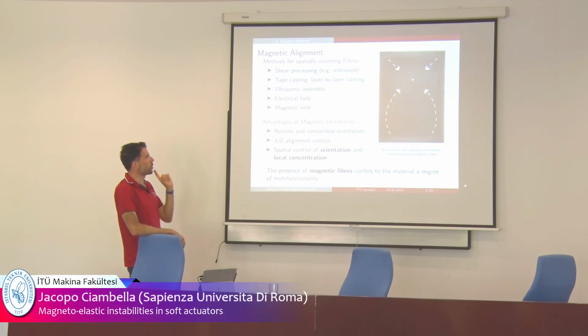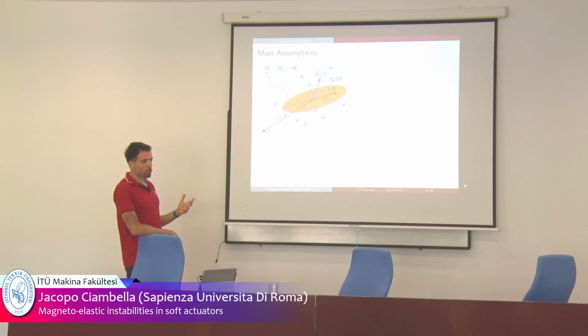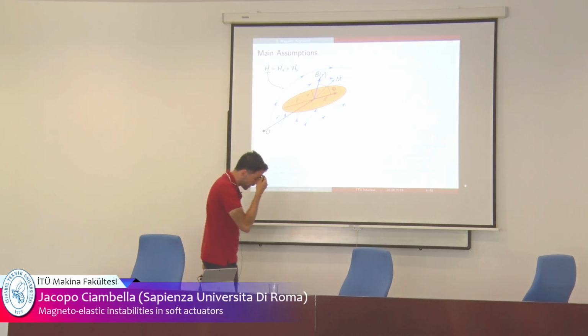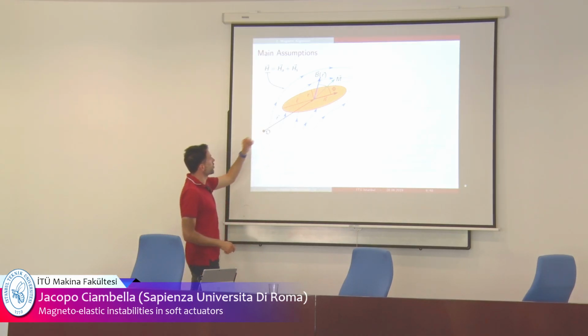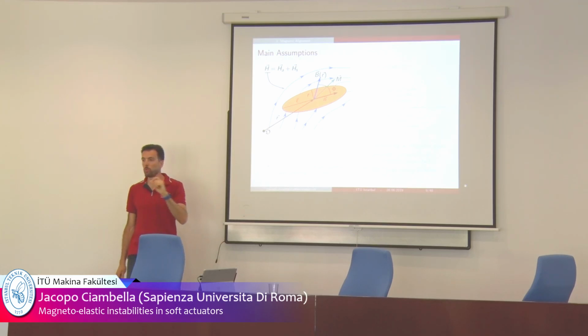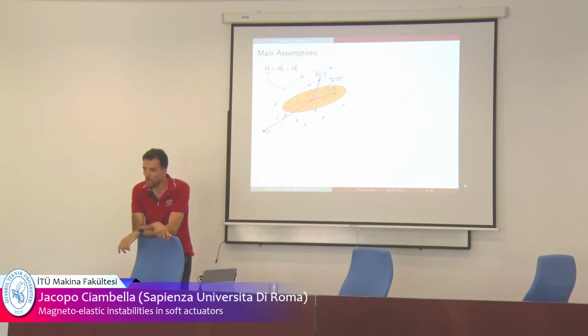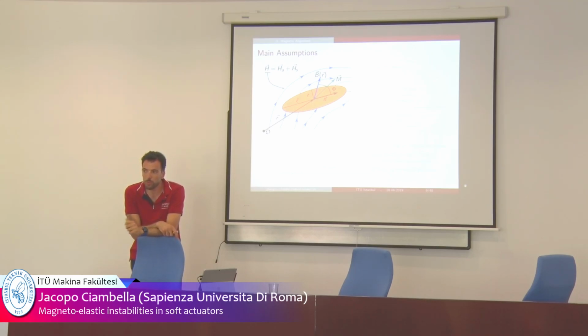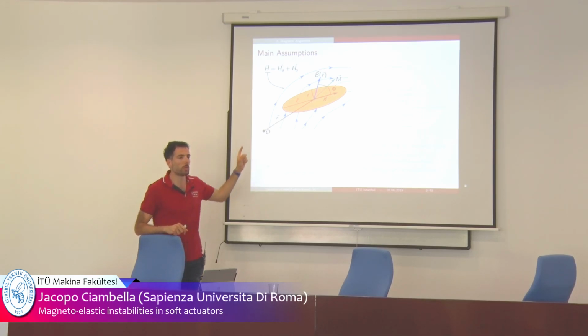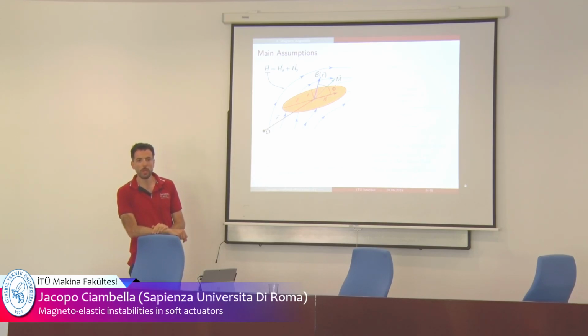And so the idea was to study exactly this process, the reorientation process, to have a very fine control over it. How to do that? Well, I will show you a very simple model to do that. First of all, let me introduce some notation here. So what I will do, I will assume that the particle is ellipsoidal. And why so? Because you have some advantages. From the magnetic point of view, you can solve Maxwell equations in closed form. And from the mechanical point of view, we want to study the motion of this particle in a viscous solution, and so you can work out the drag coefficient in closed form if the particle is ellipsoidal.